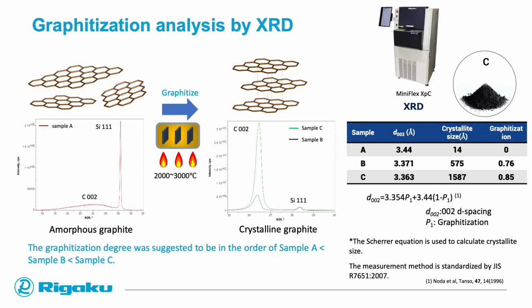For example, in this special case, the graphitization, where we analyze our graphite starting material, because the degree of graphitization is important when it comes to the battery capacity, so we can directly conclude from the results here to the later performance of the battery cell. In this special case, we have 3 different samples, A, B, and C, which differ in their crystal structure, but also, of course, in the degree of graphitization. Easy and fast measurements, and also the evaluation of these results is very simple and fast.